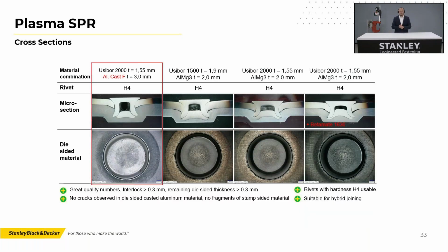So let's see some results of that. These results have also been shown at the joining event in Bad Nauheim. But again, I want to talk about the first one that I highlighted in red here. This combination is a 2000 megapascal Usibor with 1.55 millimeters into an F-temper aluminum cast. And we used, as you can see, a rivet in H4, so not hardness 6, just hardness 4, with a quite basic rivet geometry and a flat die. We were able to join this combination without cracks or any other problems with the rivet, because if you would try to join this material with this kind of rivet, you would just press the rivet flat and that's it. You would not be able to pierce through this material with any kind of rivet.